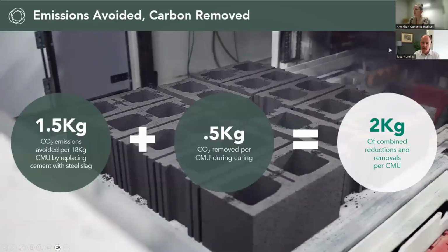So to give you a sense of the magnitude, in 1 CMU, a concrete masonry unit, which is what you see there in the picture, we're avoiding 1.5 kilograms of CO2 emissions because we don't use cement. And then we're permanently sequestering about a half a kilo of CO2 into each of the blocks that you see on the page there during the curing process. So in total, we have about a 2 kilogram per CMU impact on CO2, both through reductions and removals of the CO2.